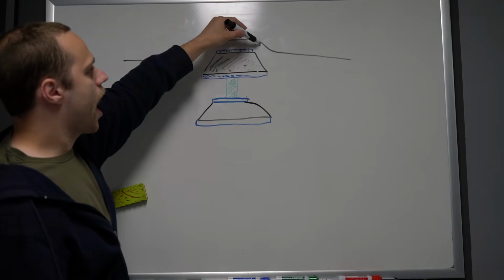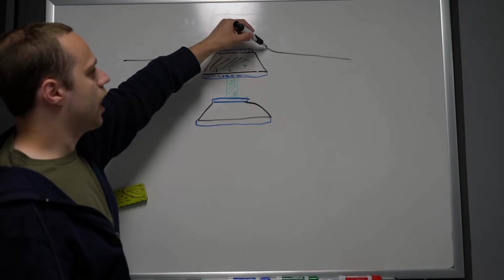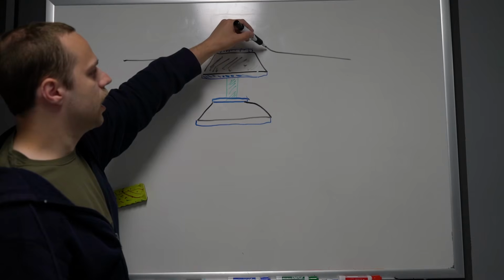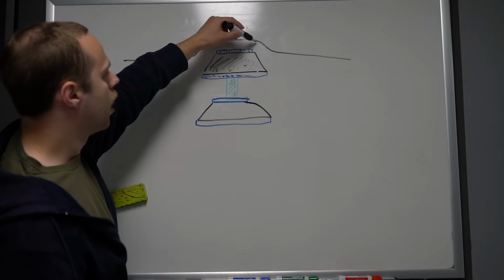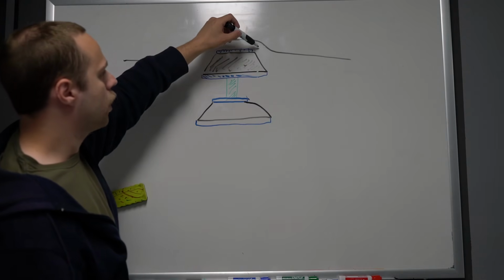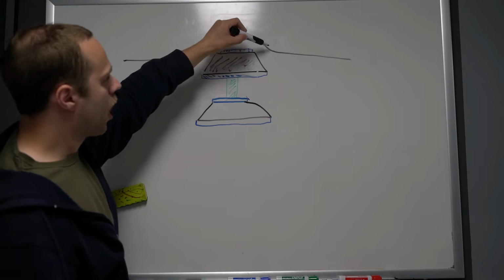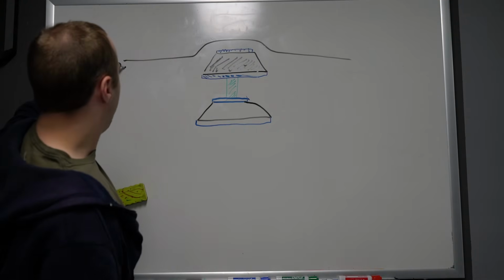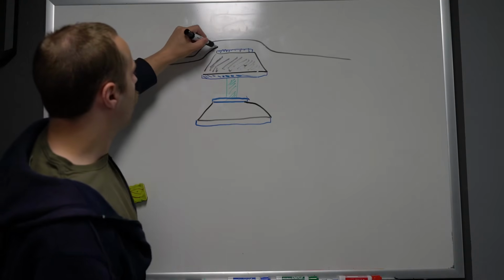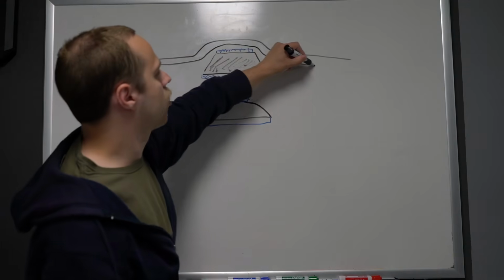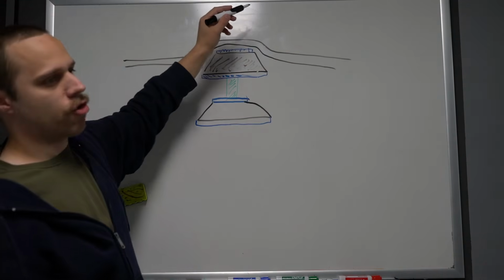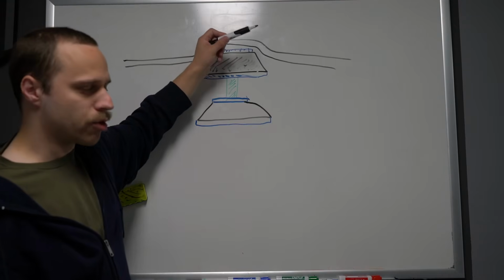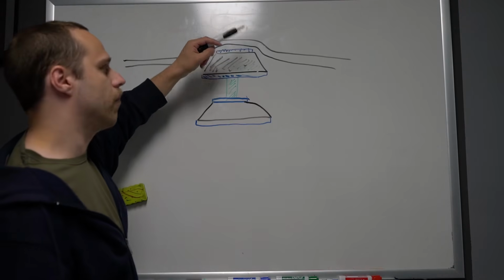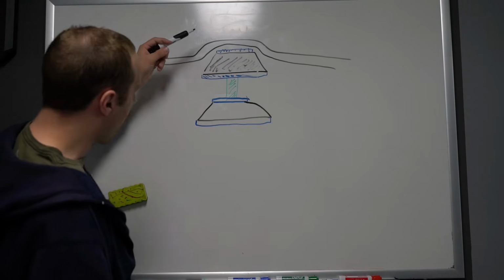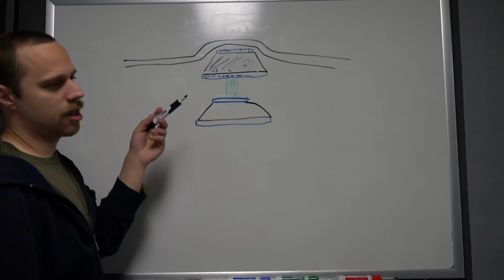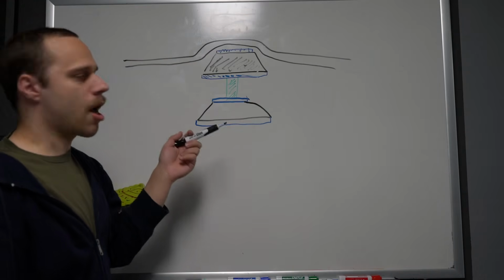And so as we continue etching in, there's usually a thin spot in the top. The top layer is actually, I forgot to mention, typically silicon nitride in the cap, and then below the silicon nitride are oxide-based dielectrics. But typically the very top is nitride because that's a little bit harder. It provides better protection to the device during packaging and handling and so on. Good news is that HF will eat nitride as well as oxide.